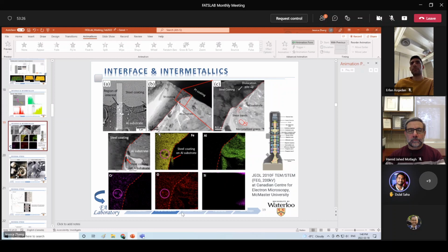So we didn't actually find any kind of trace of intermetallic. Maybe the intermetallic layer was in the nanometer scale. That's one. And to identify the effect of the intermetallics or a metallurgical bonding versus the mechanical interlocking, we did the simulation, and we found the simulation result is actually quite matching with our experimental data,